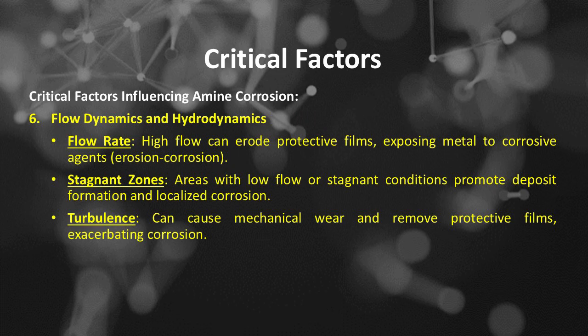Critical factors influencing amine corrosion. Number 6 is flow dynamics and hydrodynamics. Flow rate: high flow can erode protective films, exposing metal to corrosive agents. Erosion corrosion. Stagnant zones: areas with low flow or stagnant conditions promote deposit formation and localized corrosion. Turbulence can cause mechanical wear and remove protective films, exacerbating corrosion.